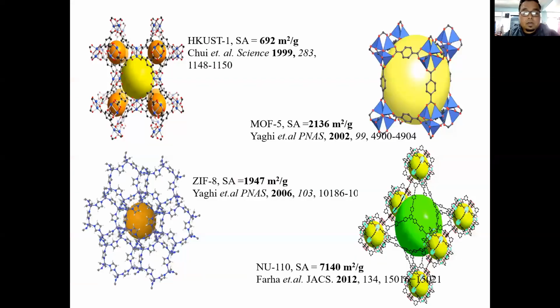So to give you a brief perspective, let's say HKUST1. So these yellow centers are all pores, vacant places. So I have designated it with space. So this is where all your guest molecules can come and adsorb. So the surface area for HKUST1 that I have shown about the synthesis is 692 meters square per gram. So this is very high. Meter square per gram. That means 1 gram of this material is going to have around 692 meters square of surface area.